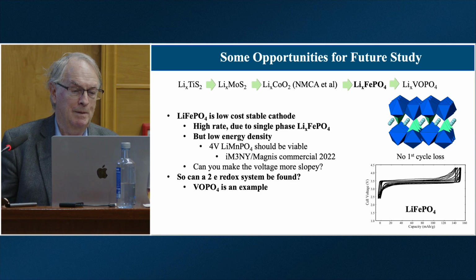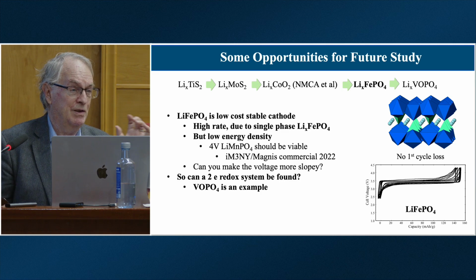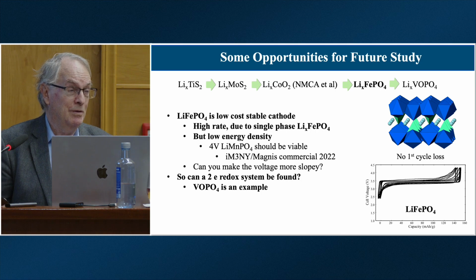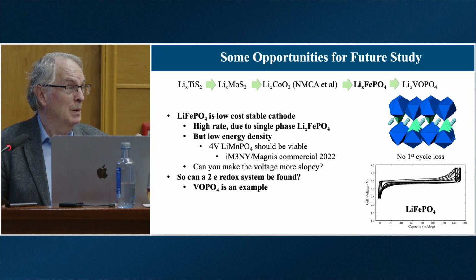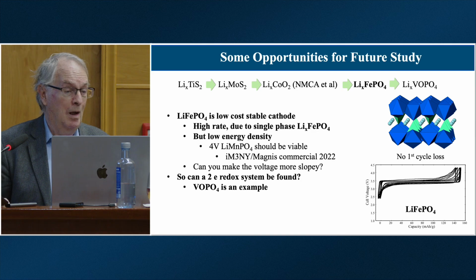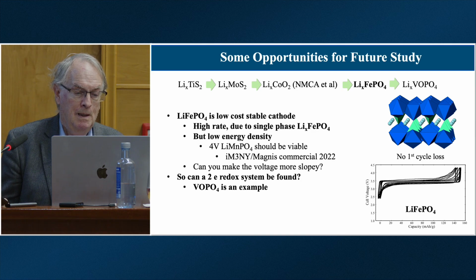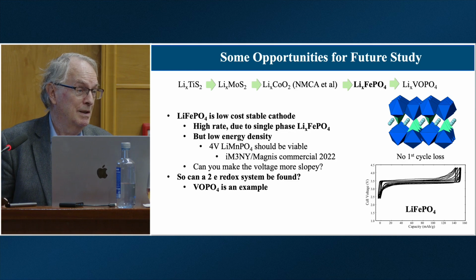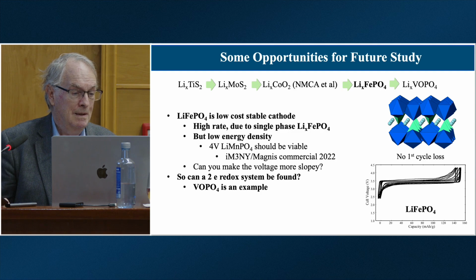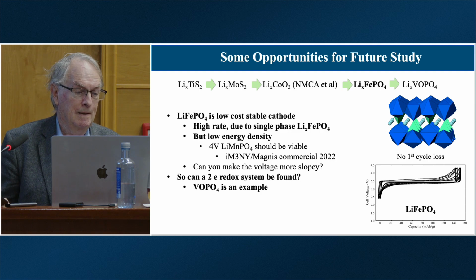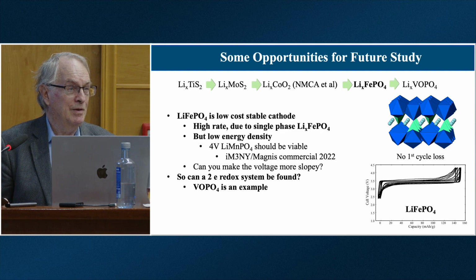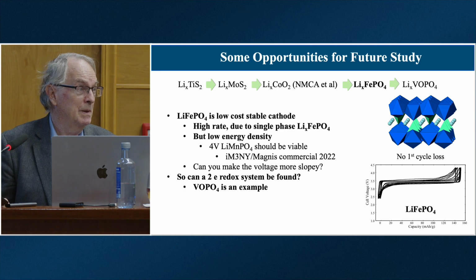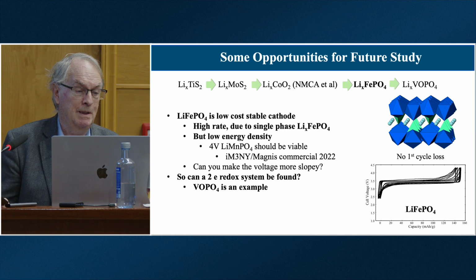Then we went to lithium iron phosphate, and that's the structure of lithium iron phosphate, a nice tunnel structure, three-dimensional structure, so much more stable than the layered oxides. It does not lose oxygen. And you can see there some cycling of this lithium iron phosphate, essentially no capacity loss, no first cycle loss, even though it's a one-dimensional lattice. So our interest now is, can we get the energy density of this material up to compete with the NMCs?